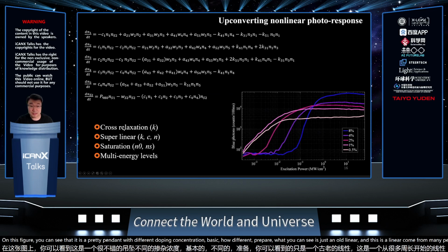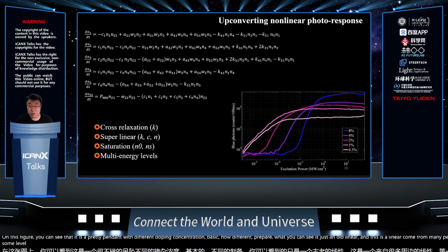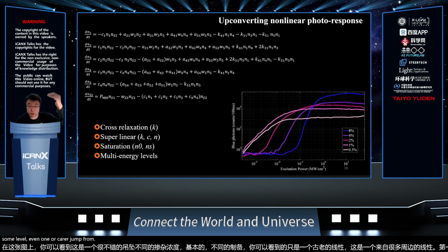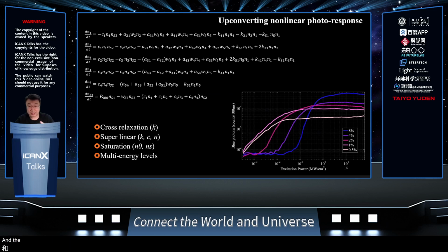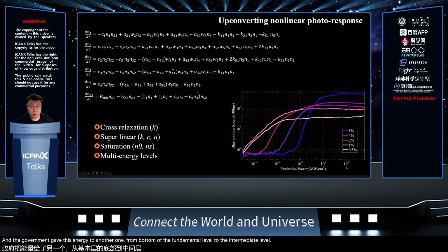The first one is this K, the cross relaxation. It means that at some level, when one carrier jumps from the top to the medium level, it gives this energy to another one from the bottom, the fundamental level, to the intermediate level. Also, if you look at the rate equation, you have this transfer rate. For some higher levels, it also depends on the carriers in other levels, because they are multiplied together. So this gives you a really beautiful superlinear curve.